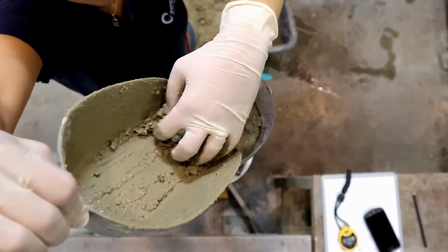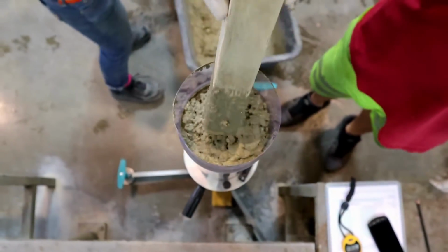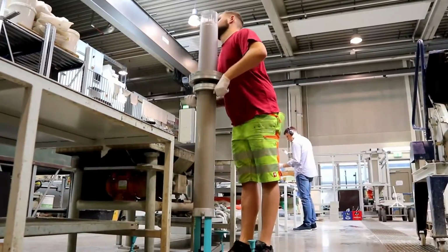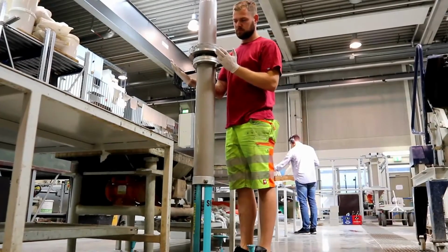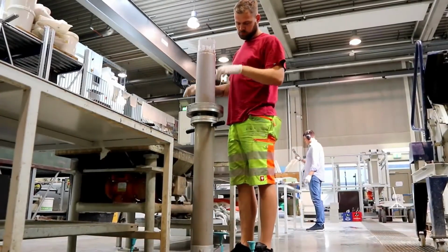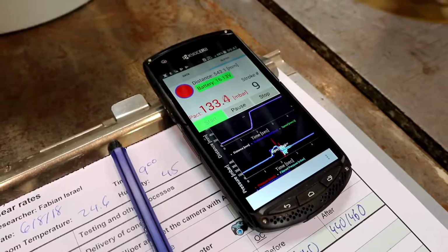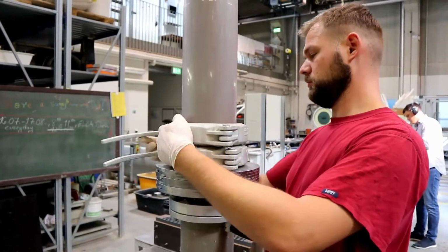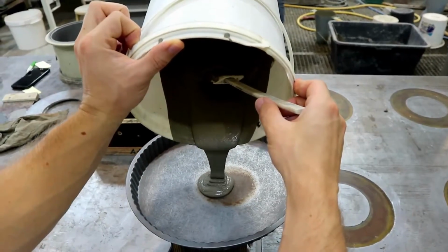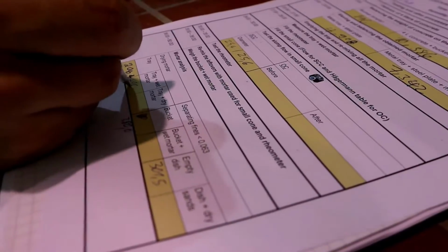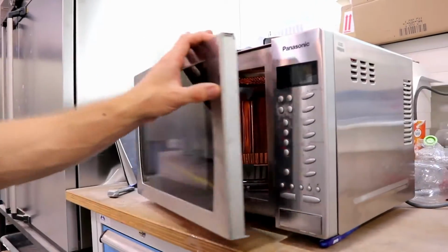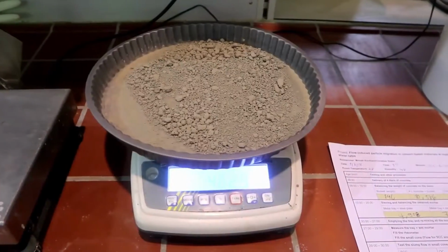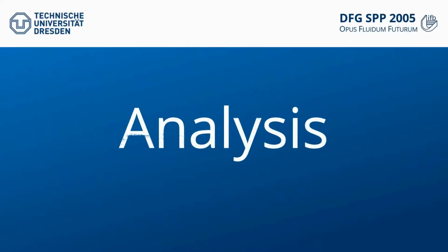Using a sliper, we are able to replicate concrete flow in a half-meter length pipeline. Here we measure the average pressure needed to pump with a specific flow rate, and during the test we increase this flow rate by increasing the coupled weight on the sliper. Meantime, we analyze the mortar composition to determine the water, sand and binder content in the constitutive mortar.